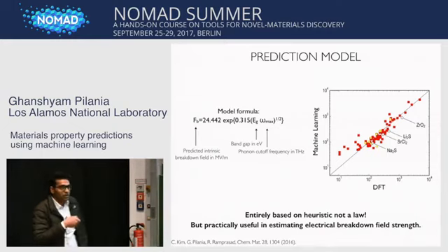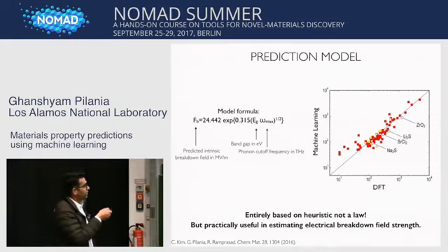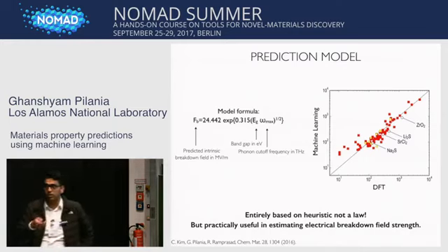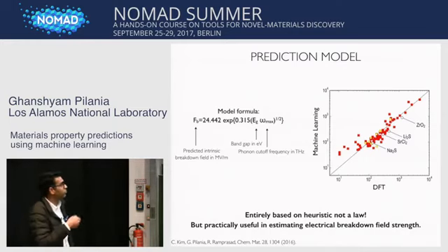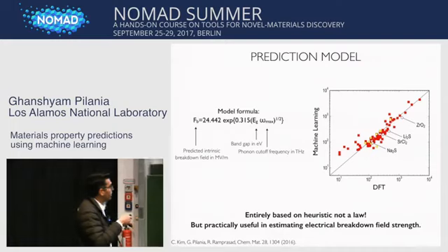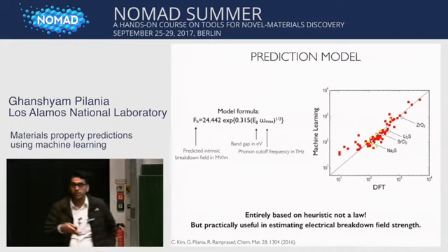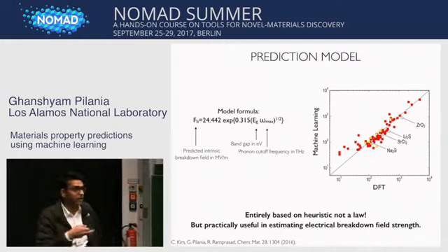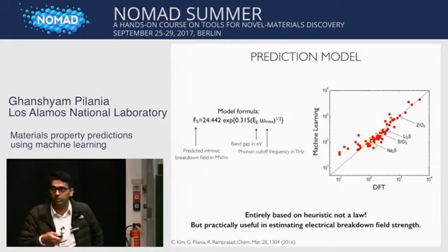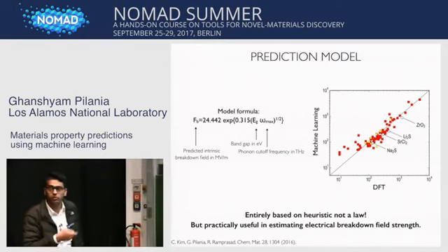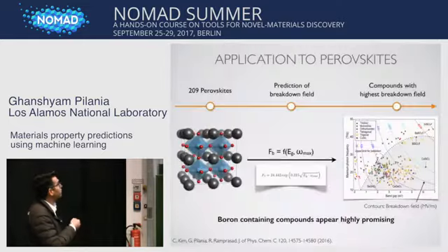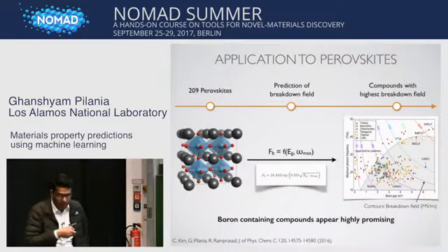But at the same time there is a disclaimer that this is based on heuristics, so this is not a law, so we should not try to read too much out of it, but it can be practically useful in exploring large chemical space and screening compounds which show high breakdown field strength. So that's what we do next. So we go to the perovskite compound space.